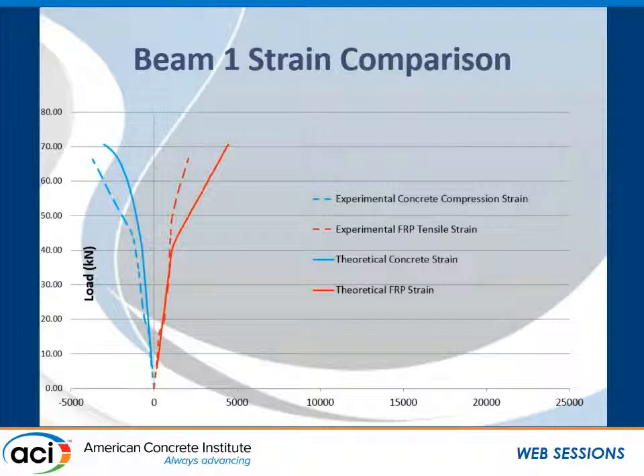And as the graph indicates, the difference between predicted and experimental strain increased as load increased. The theoretical prediction is in the solid line, blue for the concrete, red for the FRP, and the dotted line shows you our strain gauge data as the loads increased. Beams 3 and 4 from those 2013 tests followed a similar trend.